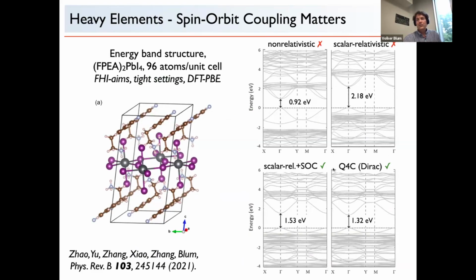And we can do better. We have a quasi 4-component method implemented in the code that solves the Dirac equation. And you can see that for something as heavy as lead, there's a small difference in the band gap, but this is actually within the accuracy limits of hybrid functionals as well. And our scalar relativistic plus spin-orbit coupling approach has worked quite well over the years.